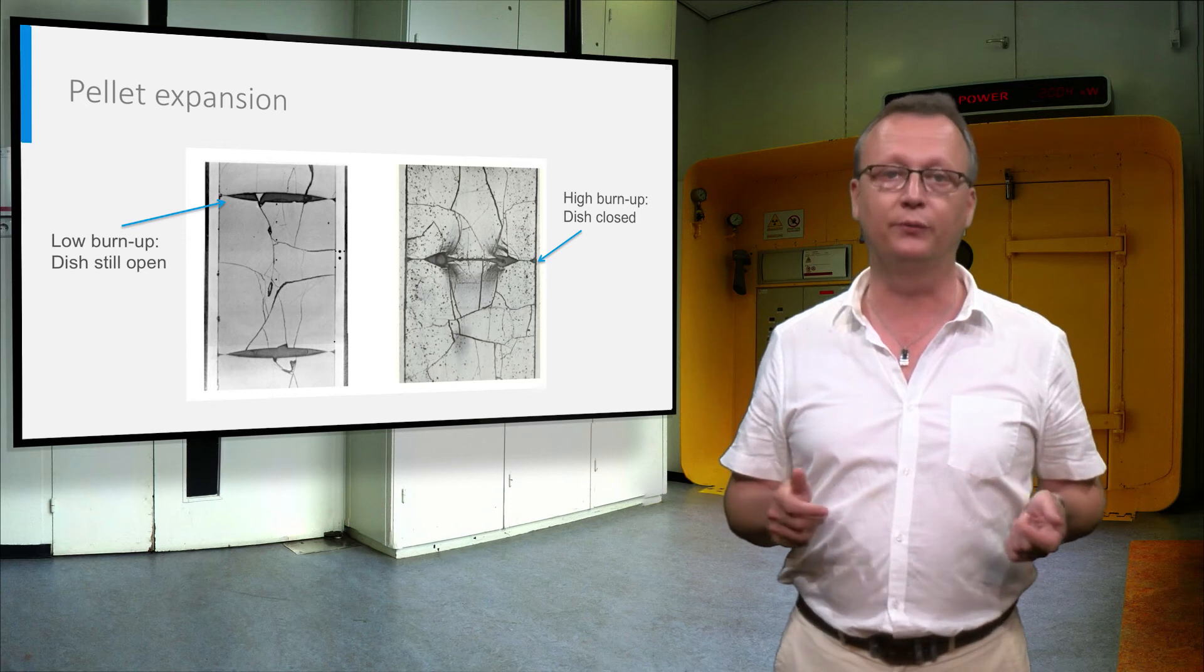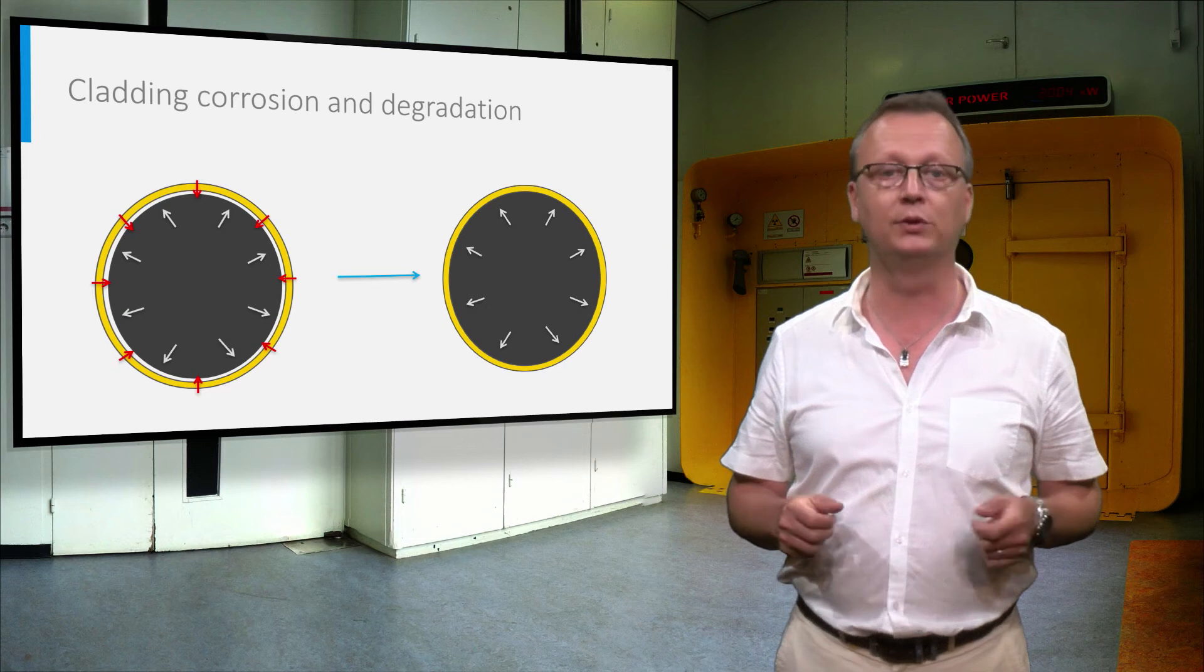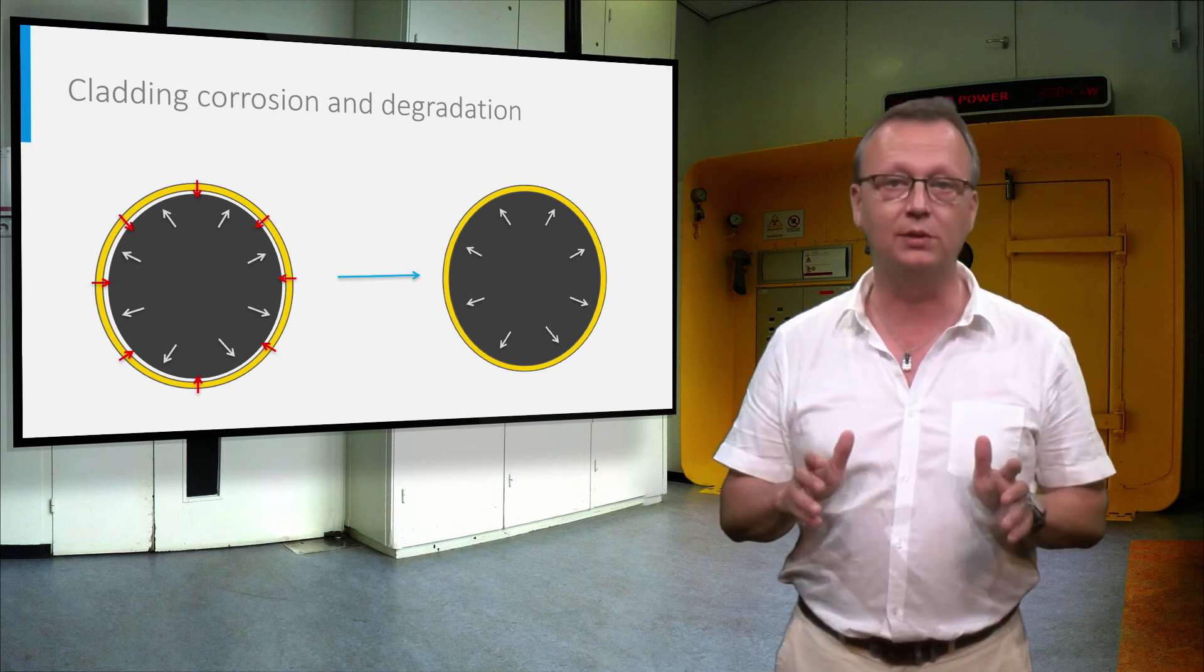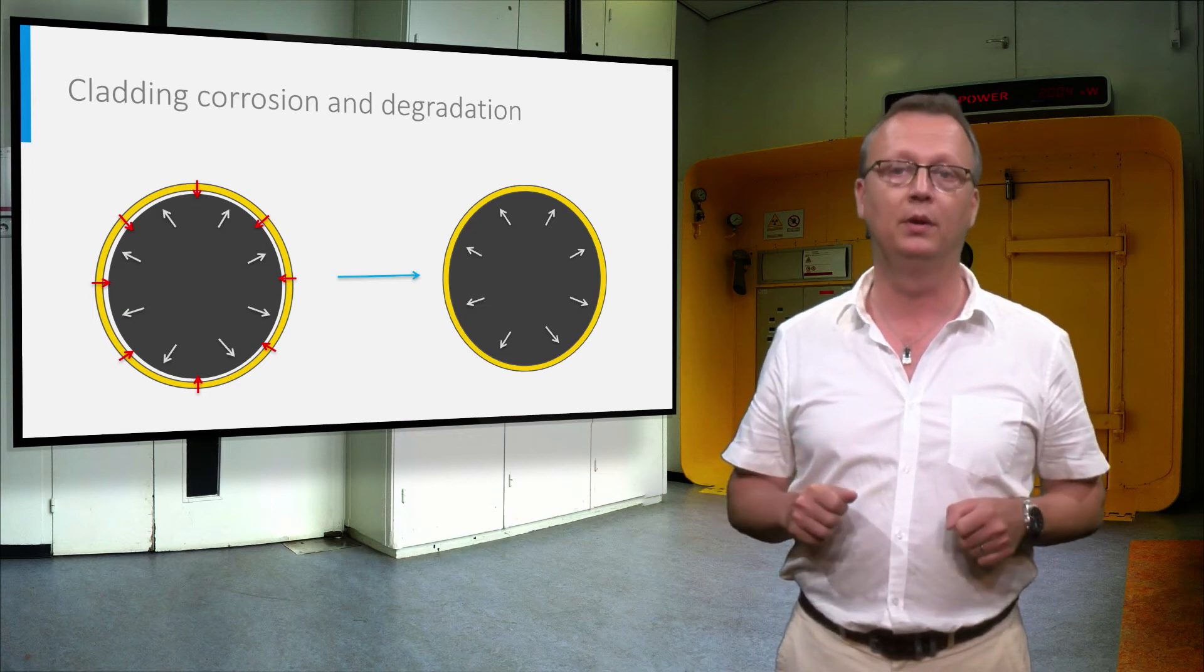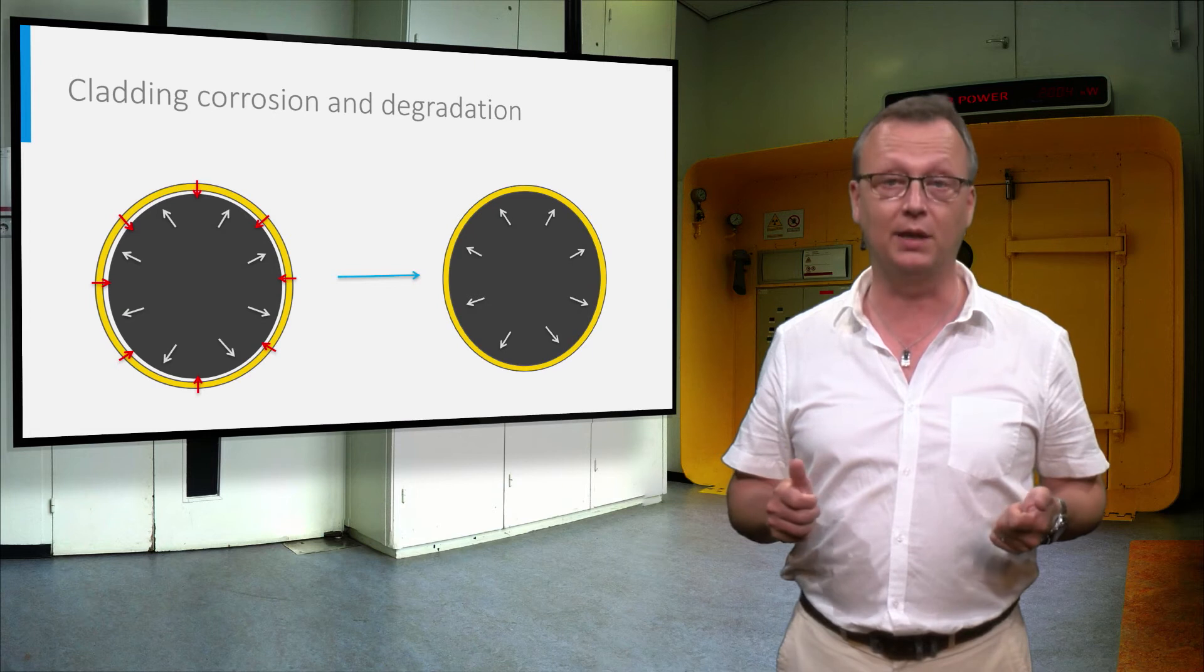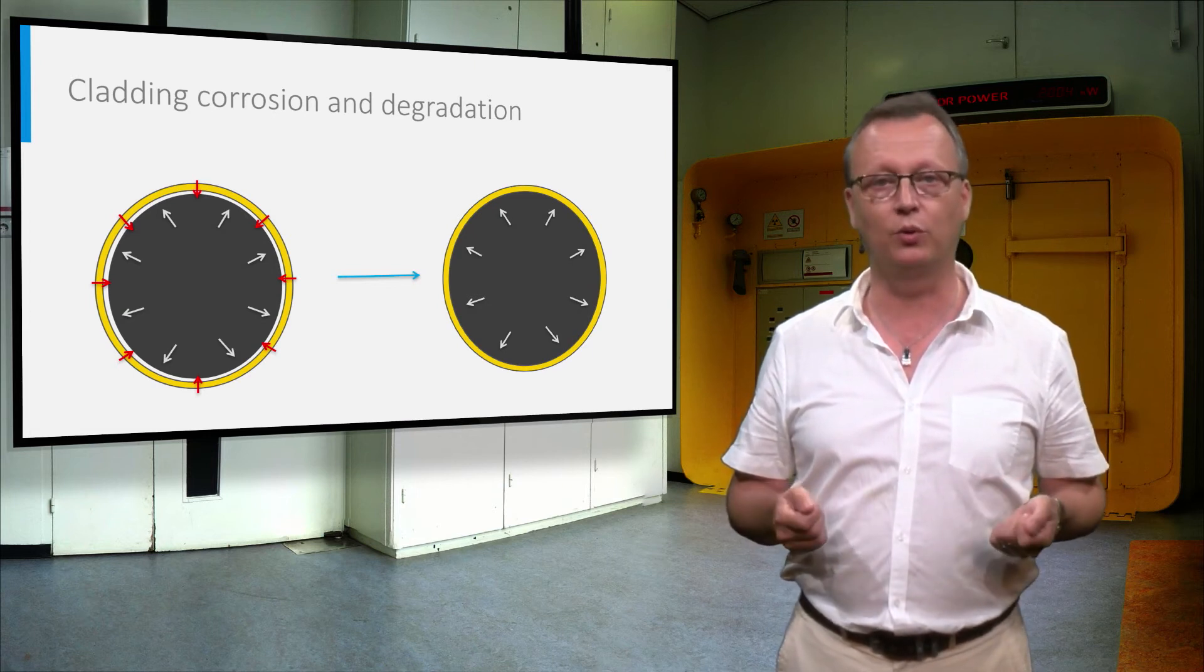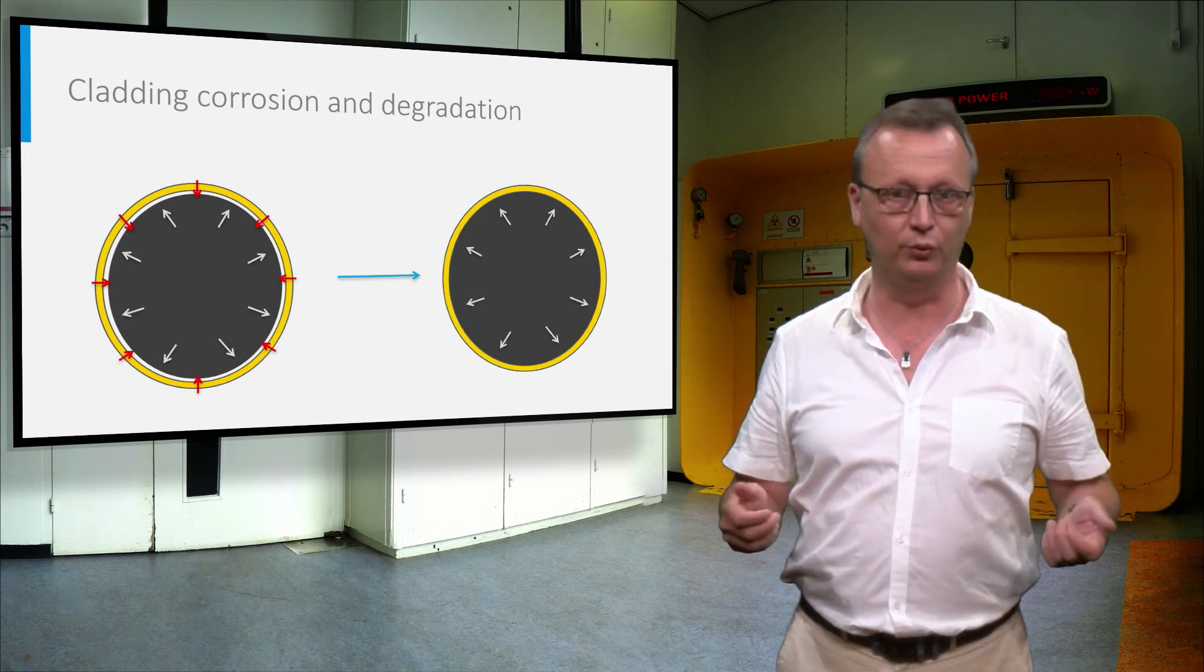As a result of the expansion of the pellet and the inward creep of the zirconium alloy cladding under the influence of radiation, the gap between the pellet and the cladding closes, and with increasing expansion of the fuel pellet with burn-up, the pellet starts to exert a mechanical stress on the cladding. This can be a possible cause for cladding failure and is a possible life-limiting factor for fuel pins.